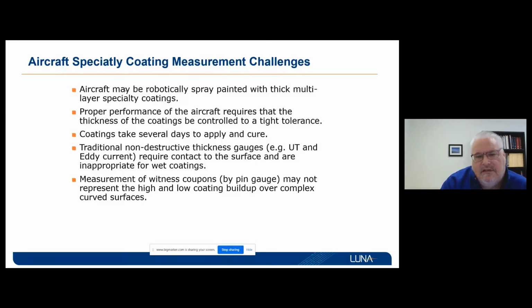Traditional non-destructive thickness gauges like UT and eddy current require contact, so you can't really use that for wet coatings. Destructive measurements like pin gauge are, of course, destructive and time-consuming to perform. Eddy current also has problems with measurements on composite materials, particularly if you're changing from composite materials, which might be carbon fiber, and then of course you have metal fasteners, and then you have curvature, and this could really throw off the thickness measurements of those methods.